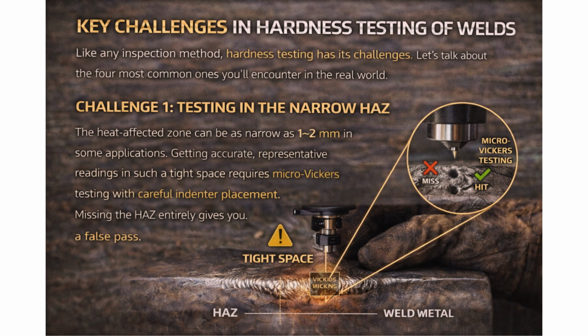Challenge 1. Testing in the narrow HAZ. The heat-affected zone can be as narrow as 1 to 2 mm in some applications. Getting accurate, representative readings in such a tight space requires micro-Vickers testing with careful indenter placement. Missing the HAZ entirely gives you a false pass.